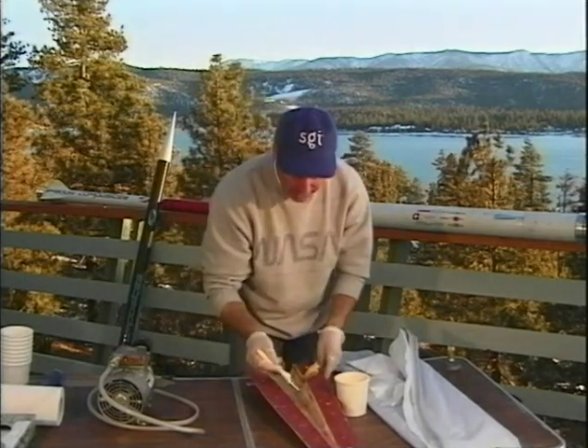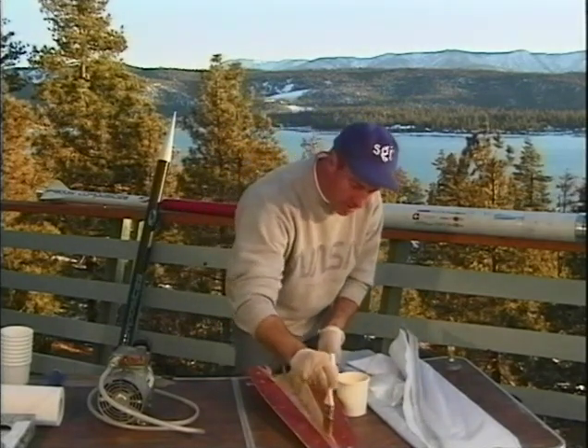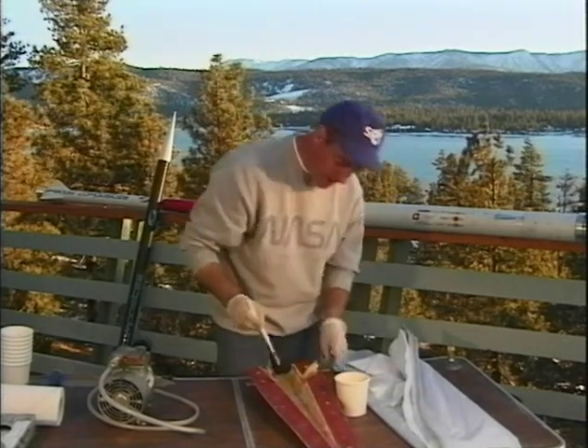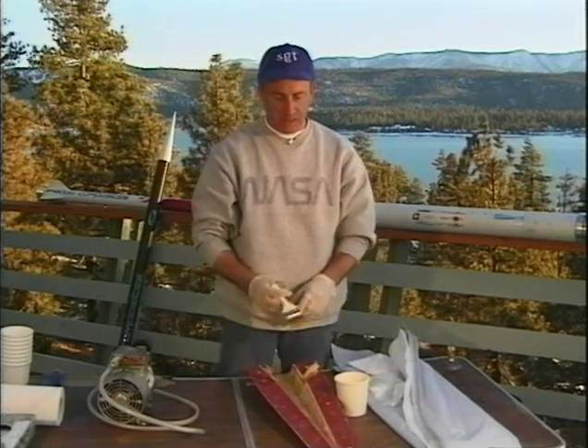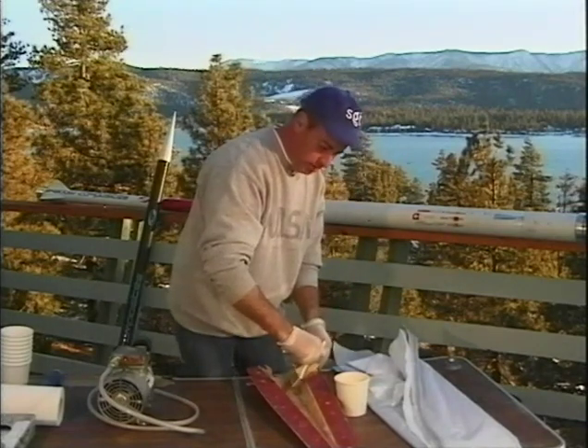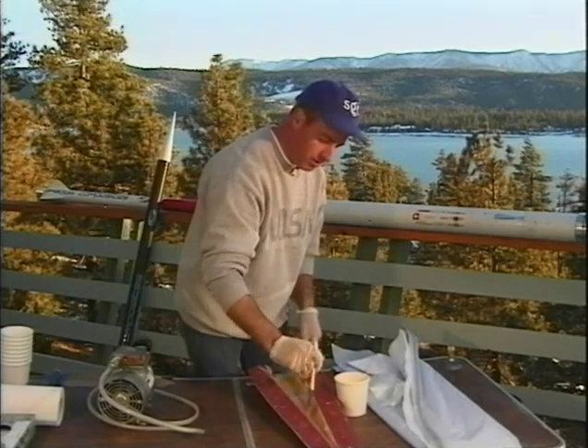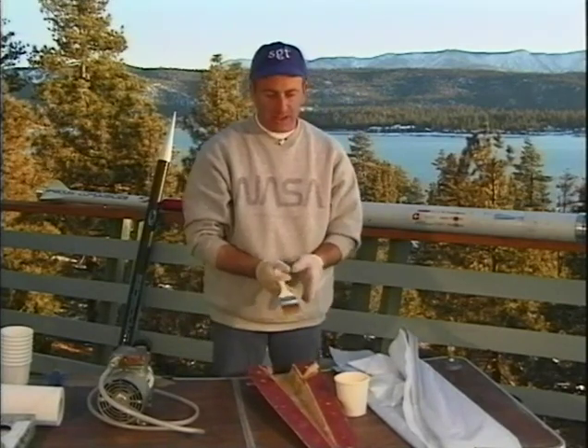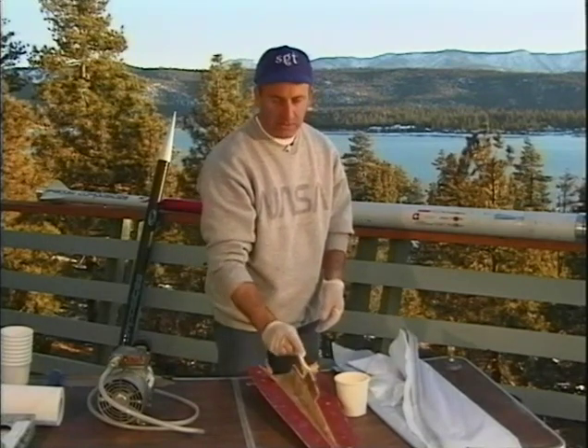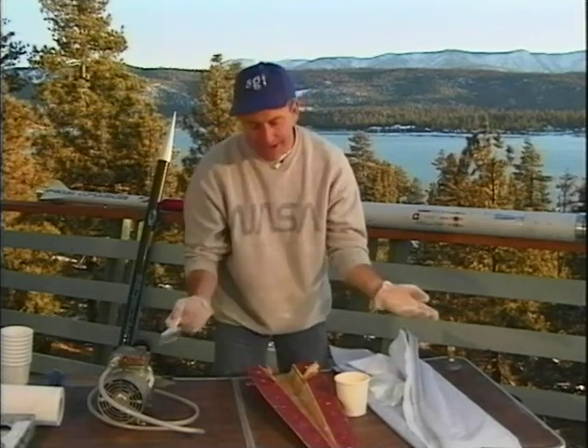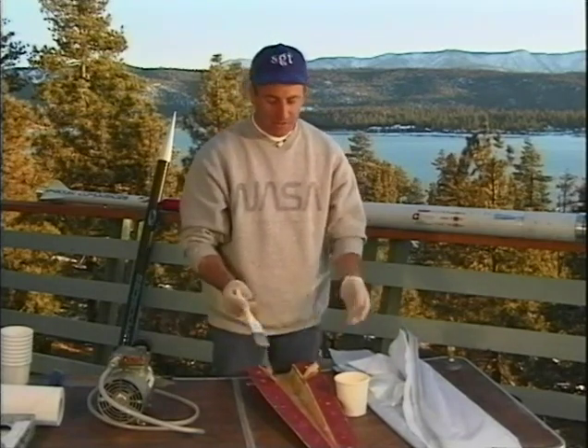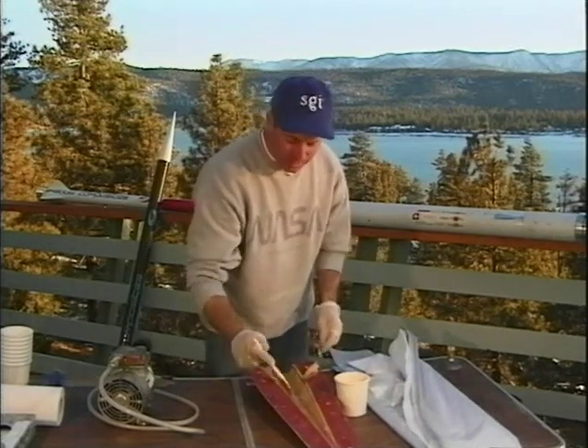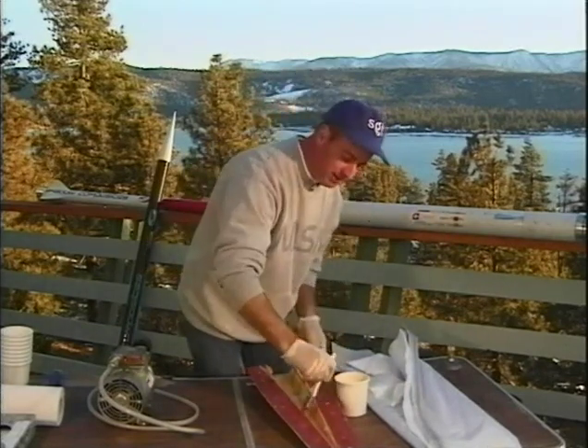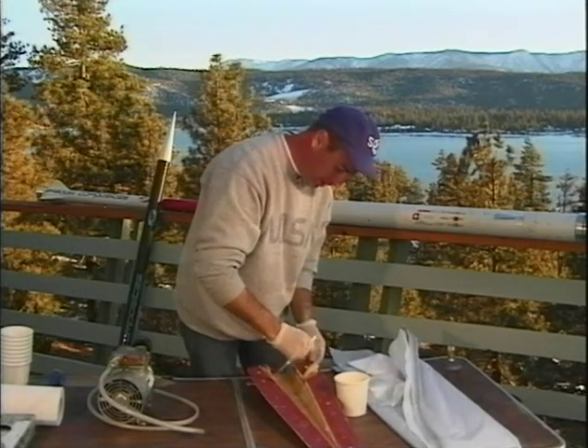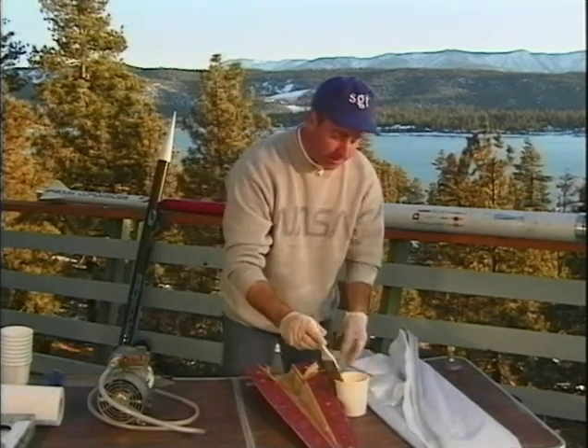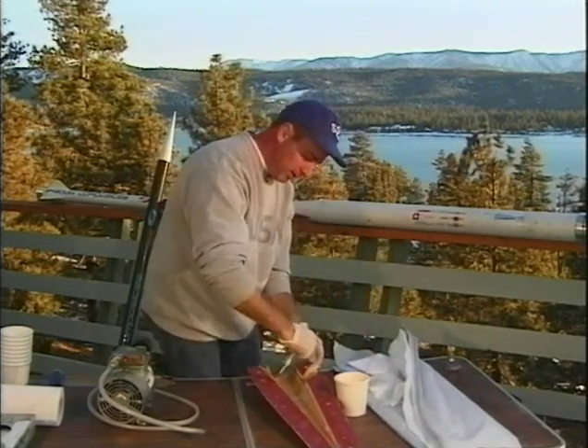Okay, you'll see the Kevlar is just hanging out. That's fine. Don't need to do anything special with it. In this case, where those just two narrow strips are there to ramp over the shoulder, the vacuum bag will suck them down to that hard edge. I like to cut the strips on the inside of a cone, though, to fit within the confines of the cone shape. I don't like to pull it out of the cone and then ask it to go over the edges and make a big side transition. The more you do that, the more it's going to want to make air bubbles along that sharp corner right there. So I like to do it this way. You can, however, make it go up and over. Just be aware that you will have more air bubbles to fill.